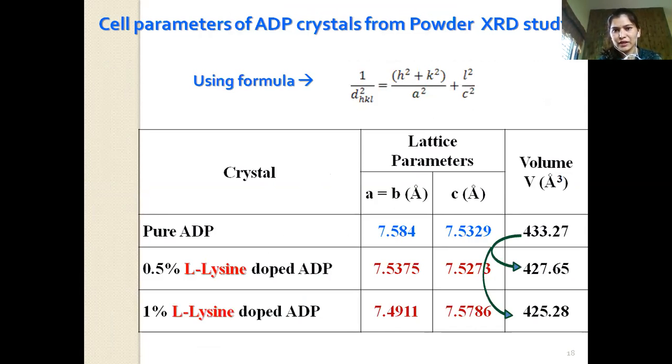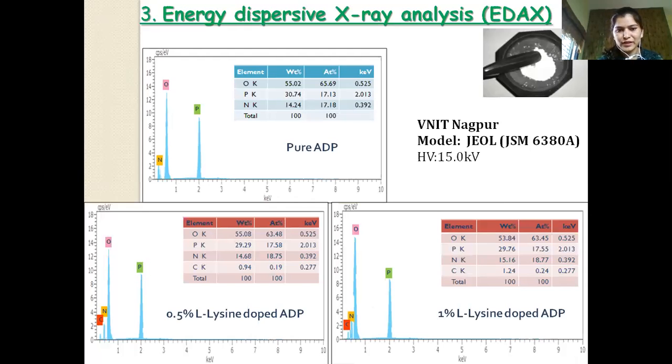Next, I have done the EDAX analysis. EDAX analysis is to investigate whether this organic L-lysine molecule has entered the lattice of ADP or not. Here, the presence of carbon atom confirms the incorporation of L-lysine molecule in our ADP crystal.